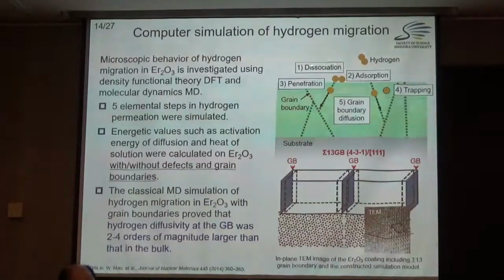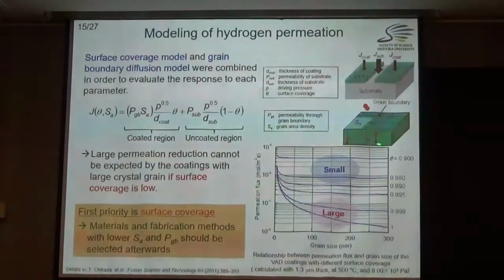This is another analysis with computer simulation. This is just a simple model with a coated region and an uncoated region, when we think about peel off or cracks in the coating. In the coating, we assume grain boundary diffusion. Then this is the permeation flux against the grain size of the coating,